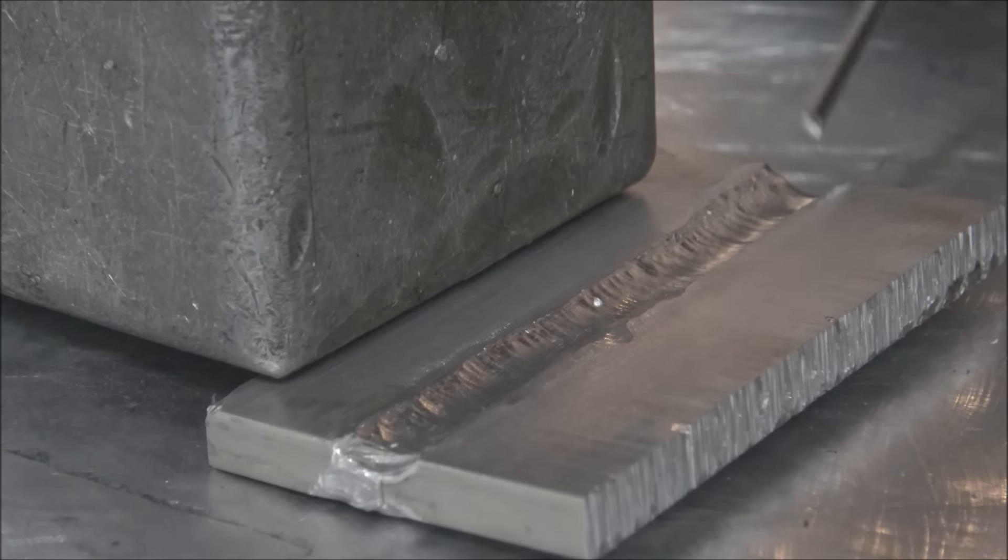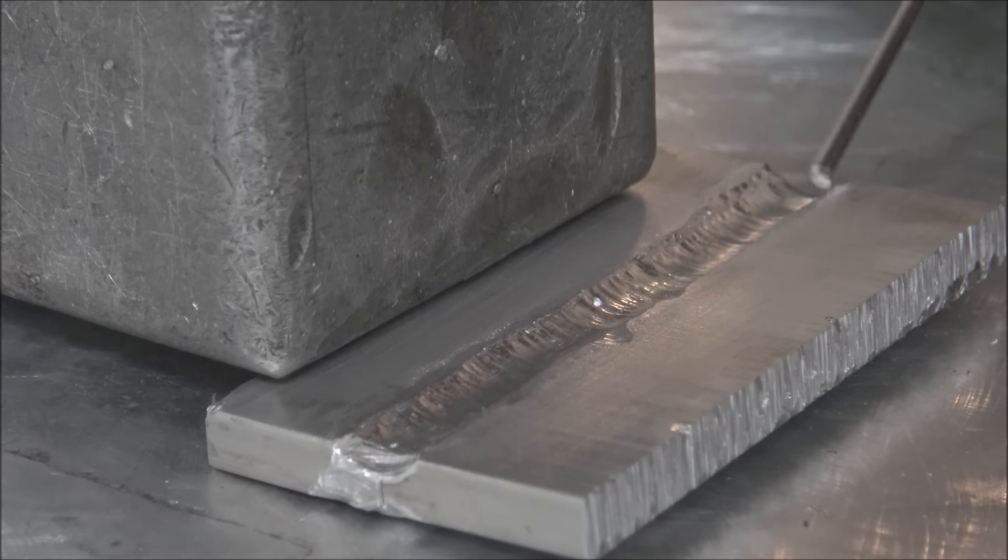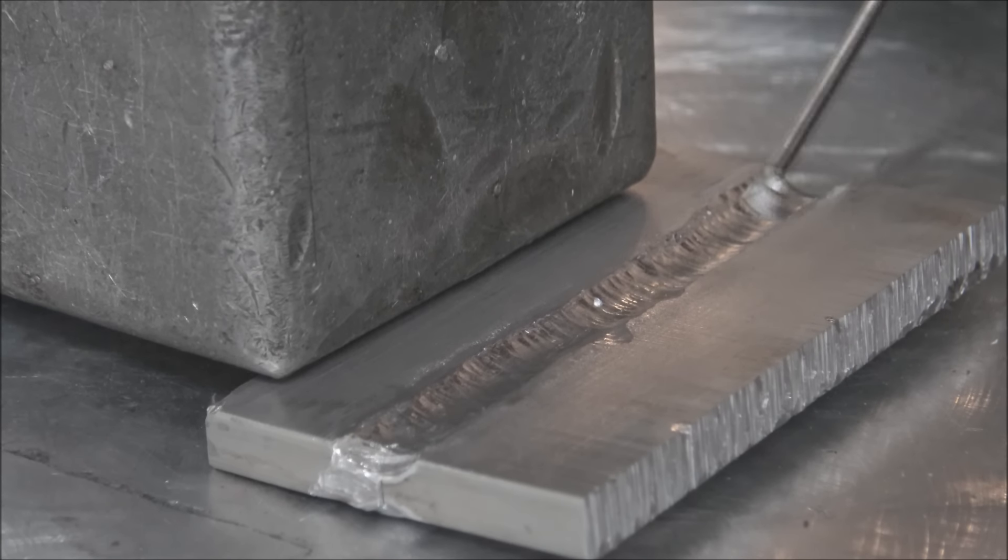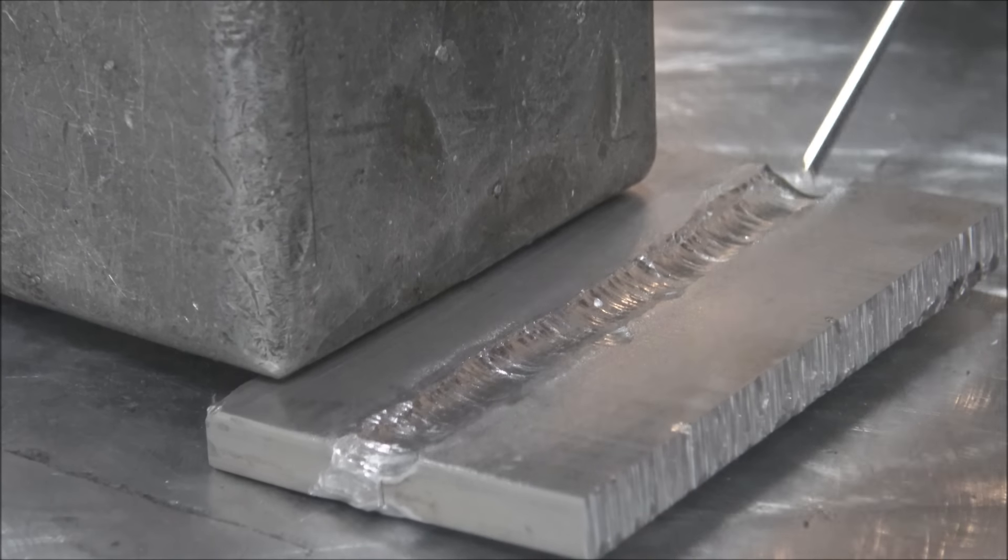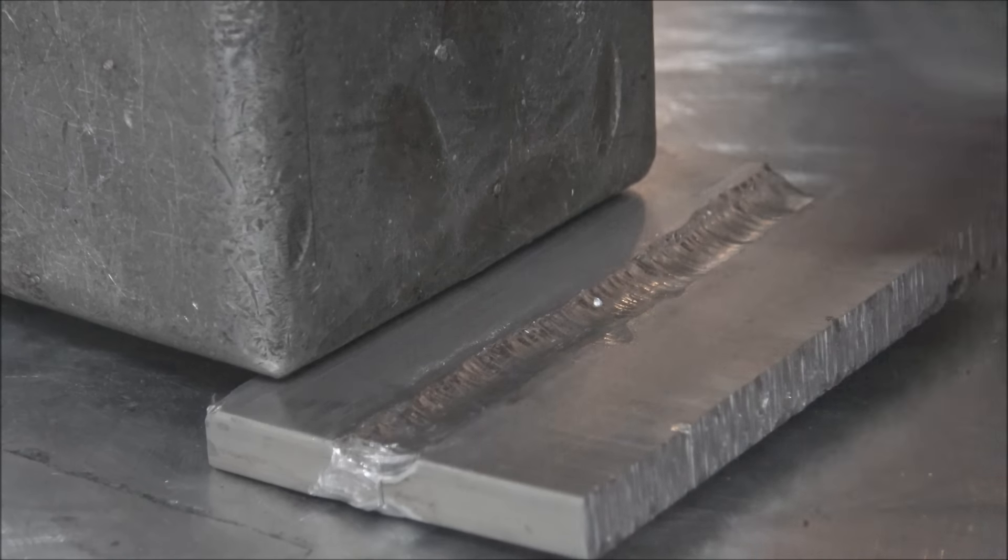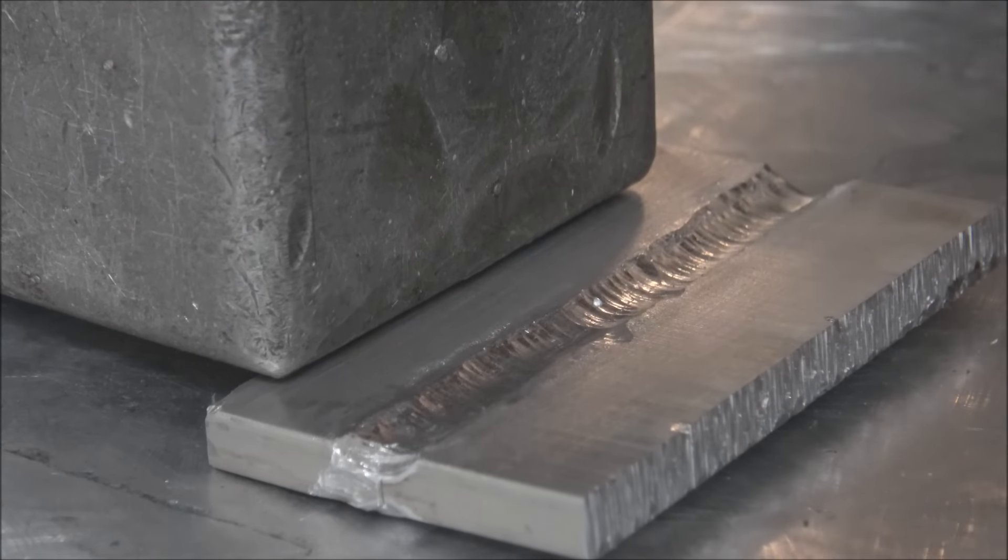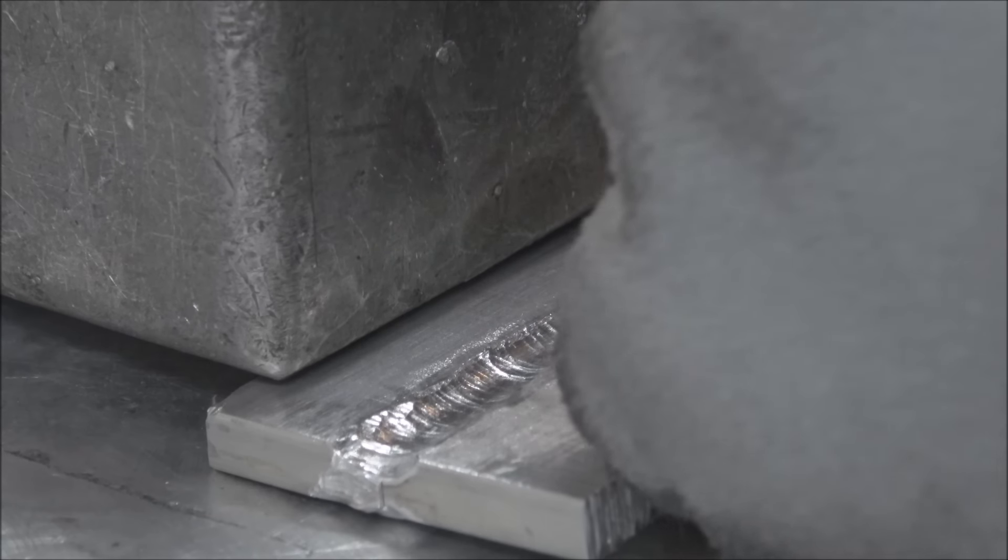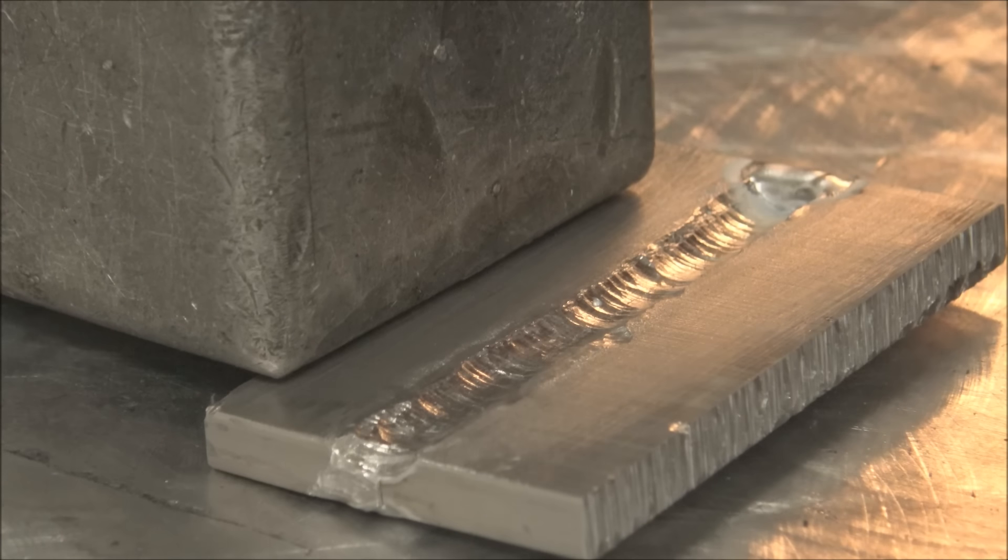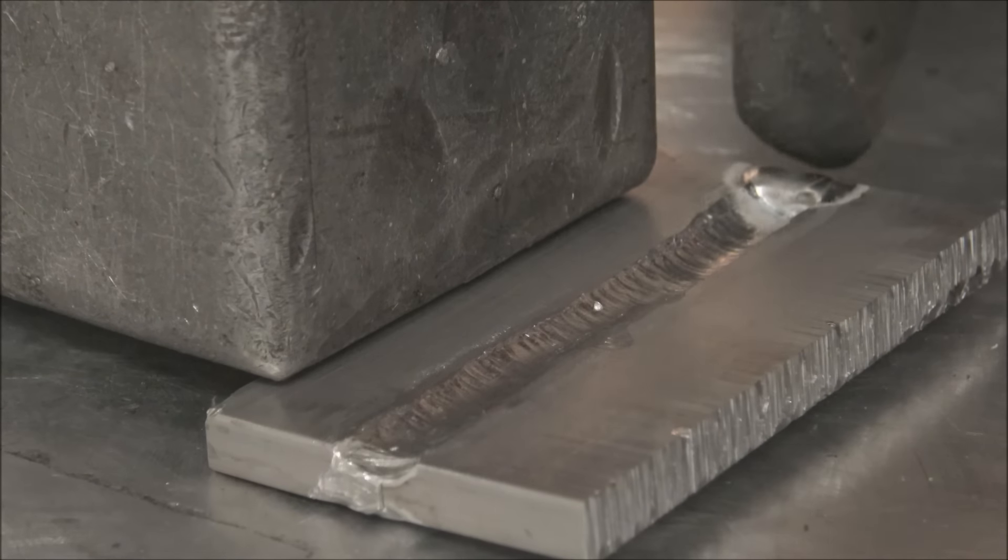And then another trick or tip you can do is add a little bit of filler rod here at the end of your weld while the part's still cool so it's easier to tie into and you don't end up burning out the end of your part and washing it out. That gives you a little dam to run into.